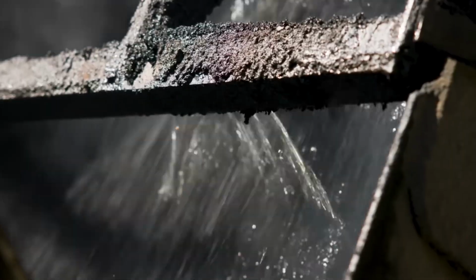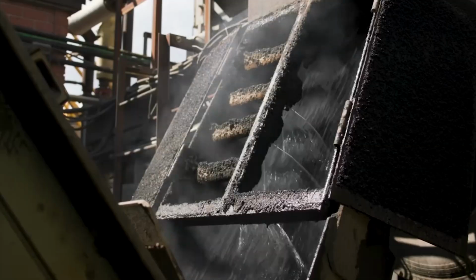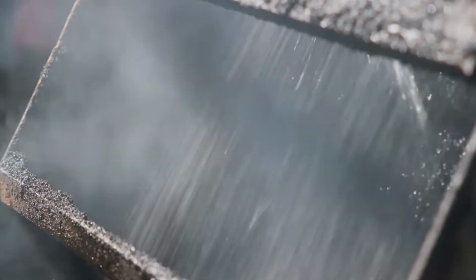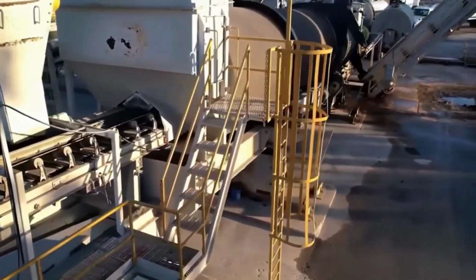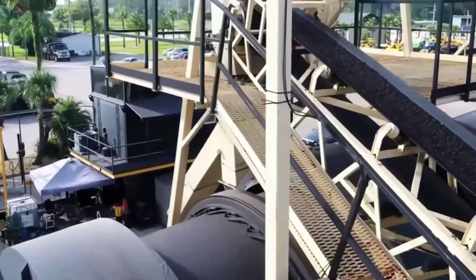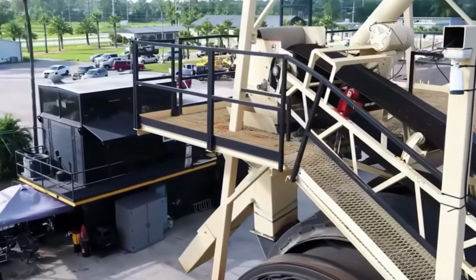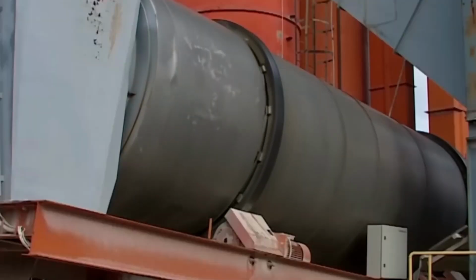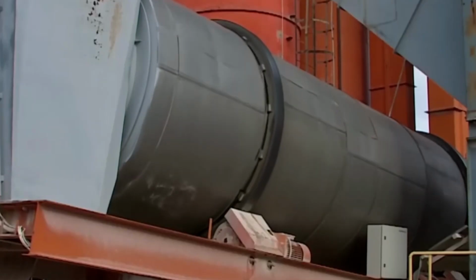To solve this, modern plants utilize counterflow drums. In this design, the heat transfer is compartmentalized. The superheat zone: virgin aggregate, new sand and stone, enters near the burner. It is exposed to the direct flame and superheated, often reaching temperatures exceeding 250 degrees Celsius. The shielded zone: the RAP enters the drum roughly halfway down, protected by a steel collar.